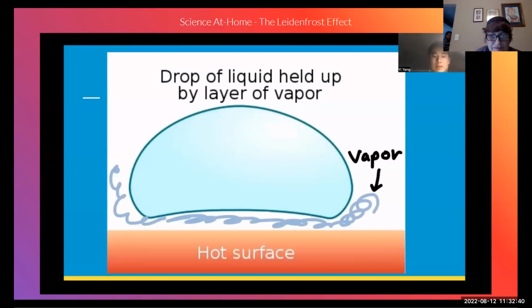The vapor conducts heat slower than the regular liquid, which means that it takes up more time for the hot surface to vaporize the rest of the droplet. This helps insulate whatever is behind the liquid. This vapor cushion stays until there's no more liquid left, so the drop will continue to levitate until it disappears. You can see this happen whether the liquid is really hot or really cold.